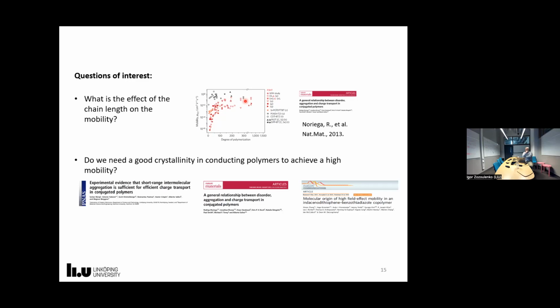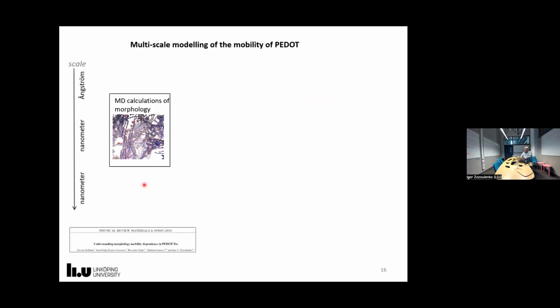Another question, very related to this one, is whether we need good crystallinity in conducting polymers to achieve high mobility. Naively, one would expect that the more crystalline the system, the larger the conductivity. However, recently there were quite a few publications where people claimed that they don't really need good crystallinity. Instead, they see very high conductivities in rather amorphous systems. This was the motivation to perform multi-scale calculations in conducting polymers, in this case PEDOT. First, let me briefly describe the main blocks of multi-scale calculations.